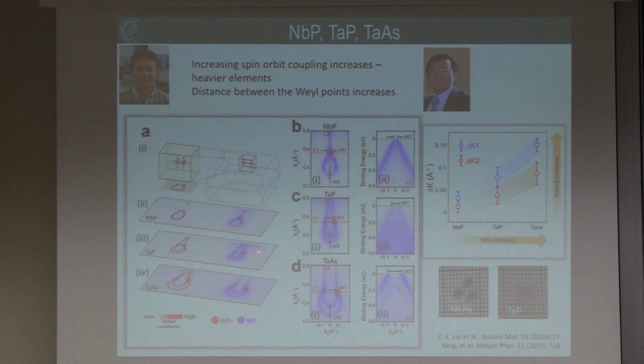You also see nicely how the Fermi arc grows with spin-orbit coupling. You see the same in the other band. The splitting between the Weyl points is also becoming larger, which shows that the spin-orbit coupling increases. So this shows that this whole family is interesting.